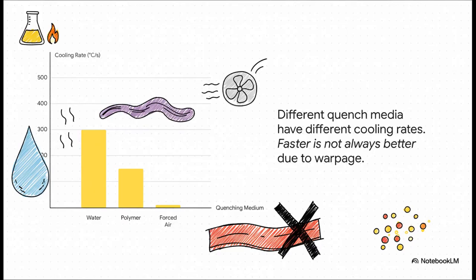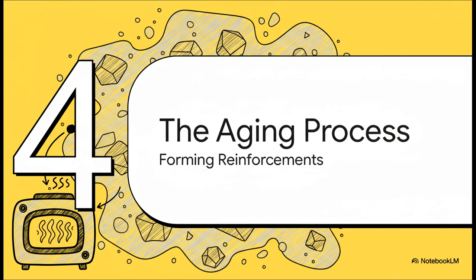And deciding how to quench brings up another critical trade-off. Plunging it in cold water, for example, is incredibly fast, but that intense thermal shock can actually cause complex parts to warp or even crack. So you might use slower options, like a special polymer solution or even just forced air. They're gentler, but you run the risk of not being fast enough to beat the clock for some of these high-performance alloys.